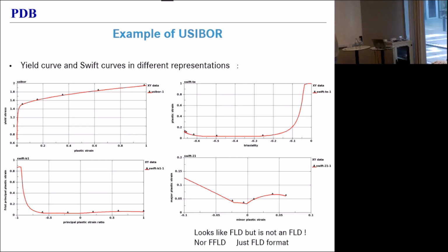One little remark, you see the red line go to 1 for a triaxiality of 0. That's a quirk of the program. In fact, it never intersects with the vertical axis at triaxiality 0. It would intersect at infinity. In other words, this criterion clearly confirms that there is no localization under pure shear conditions, that your fracture under pure shear conditions is brittle. And you don't need regularization there.